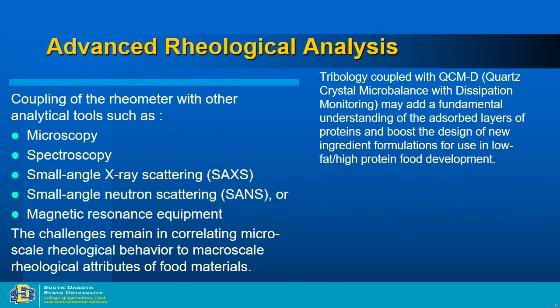And these are some of the opportunities available: microscopy, spectroscopy, small angle X-ray scattering, small angle neutron scattering, or magnetic resonance equipment. These technologies can right now be coupled with the rheometer, so that we can understand a lot more. Because currently what we are doing is rheology testing, getting the information, and trying to correlate with the structure, the microstructure, and that is not effectively happening now.